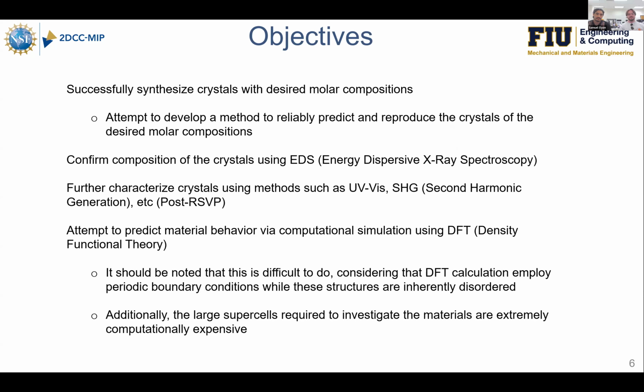And then after synthesis, obviously we characterize using EDS from the SEM just to confirm that the atomic percentages were what we would expect of those molar compositions that we had synthesized them with. And then further characterization of the crystals, especially UV-vis and SHG, is needed. These were actually done, due to time constraints, by one of our mentors, Yasu, who sent us the data afterwards.